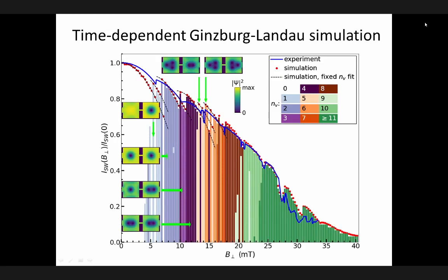And then if you look at the strength of the order parameter in the vicinity of the bridge, it tells you that when a vortex enters, the Meissner currents don't need to be so strong anymore because some part of it is now taken over by the vortex.